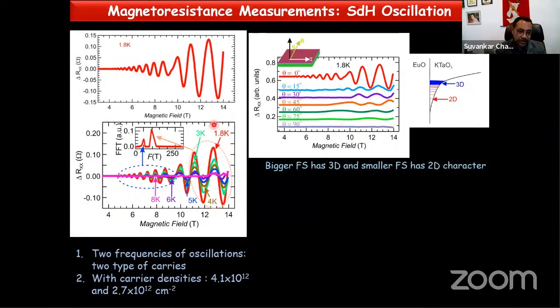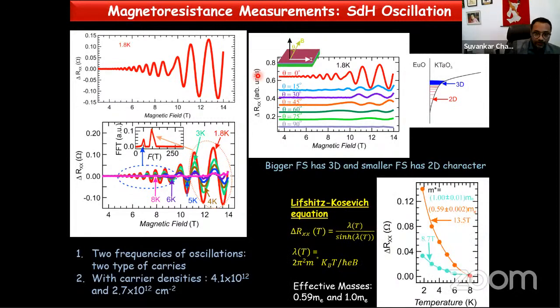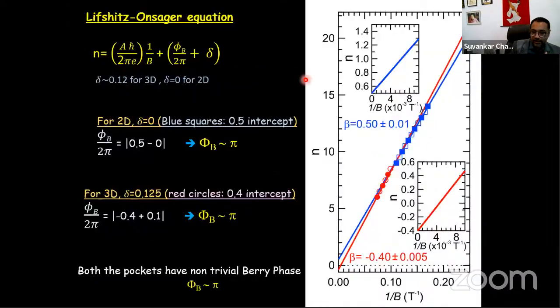In addition to that, we could see the quantum oscillation in resistivity as a function of applied magnetic field, which is known as Shubnikov-de Haas oscillation, and it shows 2 types of oscillation, which we could figure out correspond to one 3D and one 2D channel. So the important point is, when we plot this as a Landau fan diagram, it doesn't go to 0, and we could see the appearance of a non-trivial Berry phase in the system.